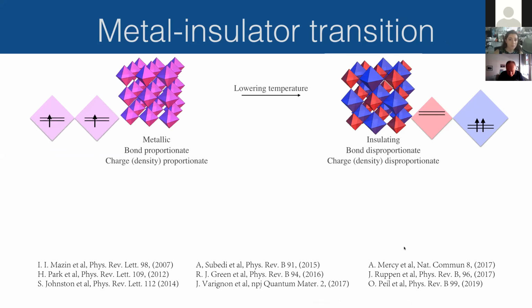Okay, so let's talk about the metal insulator transition. This is probably the most famous aspect of the rare earth nickelates. So at high temperature, and this is just going back to the low energy picture where I forget now about the oxygen ligand, you will have one electron in the EG orbital for every nickel. And that's important. It means that every nickel is identical in this state. All the oxygen octahedra are the same size in this state, so we say that it is bond proportionate, and it is charge proportionate as well. This is the metallic state.